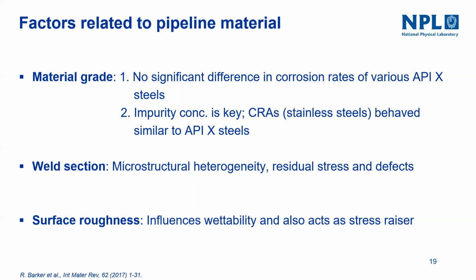And the well section has microstructure heterogeneity and residual stress and defects. So we have seen from the previous Frank's talk, there could be a significant difference, and it can cause corrosion and also contribute to stress corrosion cracking, but not many studies exist in this. And surface roughness of the pipeline, this is the internal surface, can increase the wettability and also act as stress raisers.